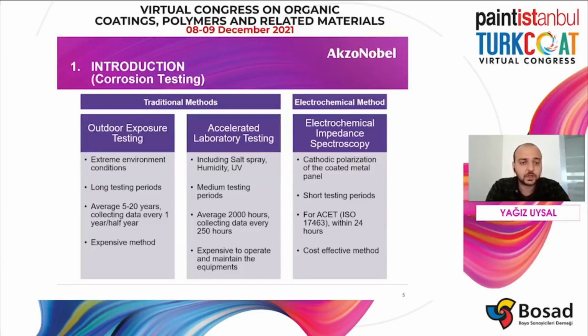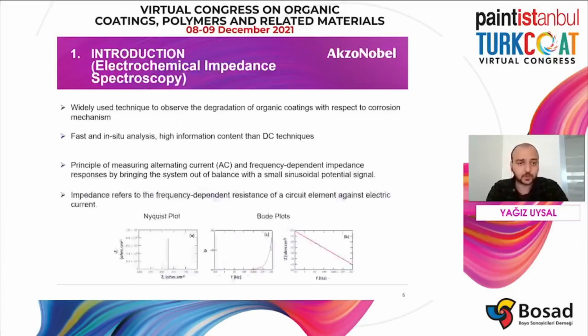It has very long testing periods, such as 5 to 20 years, and it's an expensive method. And accelerated laboratory testing includes salt spray, humidity, and UV cabins, and it has medium testing periods, such as 1,000, 2,000 hours. And it's also expensive to operate and maintain the equipment. Another method is electrochemical impedance spectroscopy. It's based on the cathodic polarization of the coated metal panel. It has shorter testing periods, and it's a cost-effective method.